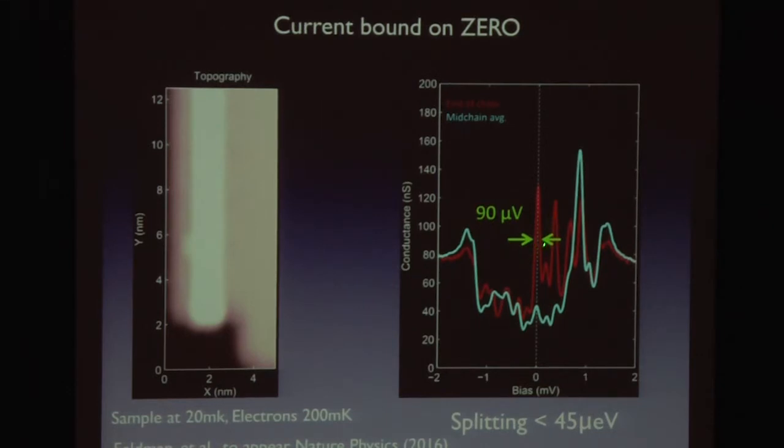And basically, he was able to show that within the resolution of this experiment, within 45 micro eV, these particles are bound to 0 energy. There are some STM experts here from Jenny Hoffman's group, and they probably could tell you that it's very, very hard to push this much further in the STM world to get this to even better resolution. So we are almost at the edge of what is possible with our technique.